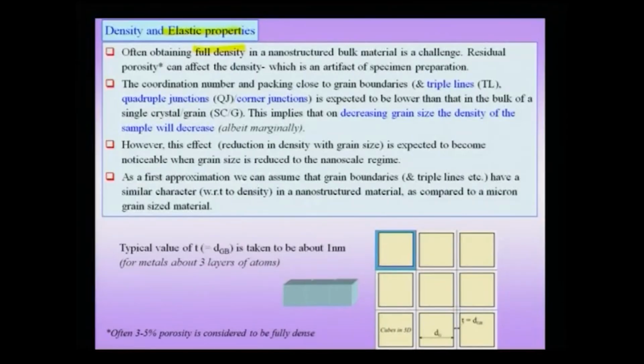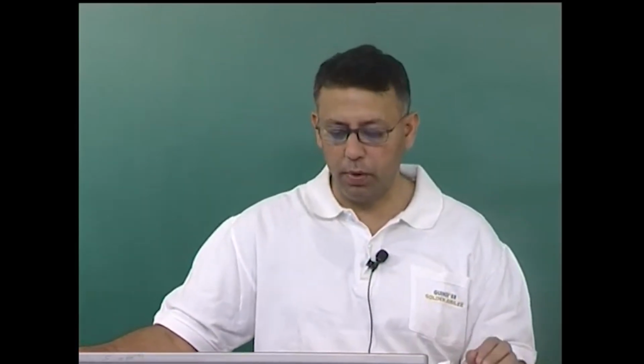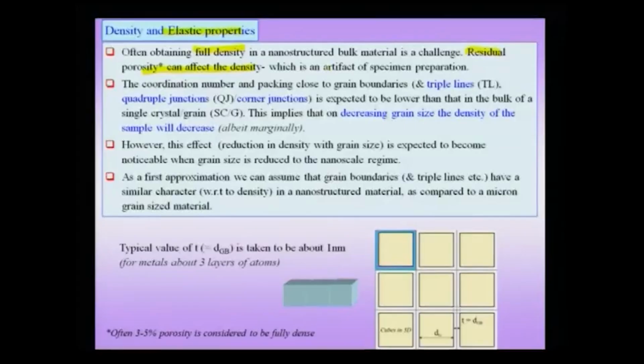The problem with nanostructured materials or nanostructured bulk material is a challenge, because often full density or close to the theoretical density cannot be obtained, and residual porosity can affect the density. So, in our arguments we always have to keep in mind that when you are talking about density of nanostructured materials, there could be an issue of porosity, and this porosity could drastically affect the properties, one of them being the elastic properties. And we would like to get rid of this artifact which is coming from the specimen processing or specimen preparation.